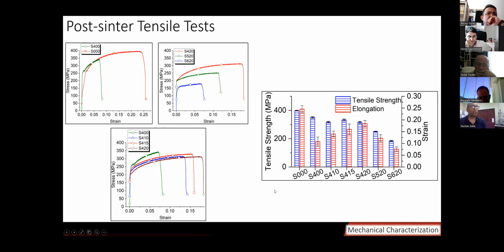Actually, it is a good thing to see that the presence of a larger fraction of iron boride phases does not have a dramatic effect on the tensile behavior of the wires, because tensile strength is not the only criterion for the mechanical properties. We have acquired a very overwhelming high hardness in the cores of the wires, as I have shown you in the previous slide.